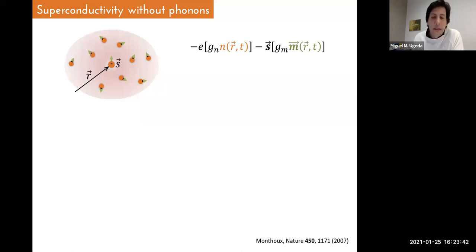However, let me go back for a second to non-phonon-mediated superconductivity. How is it possible that superconductivity emerges without the presence of phonons? Okay, so imagine that there is a soup of quasiparticles in a superconductor. And basically this is the effective field that this particular quasiparticle feels when it's surrounded by other quasiparticles. This term is basically proportional to the charge density times the charge of this particular electron. And there is a second term that accounts for the magnetization that this quasiparticle feels at this particular point in space times the spin of the electron.